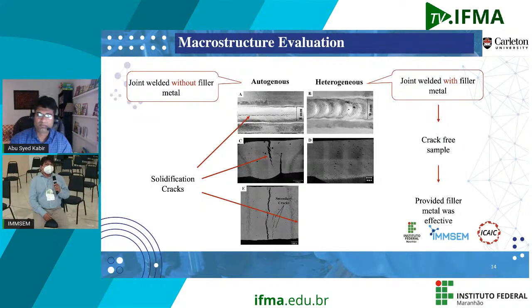So this is the output. We created two different welds. One is autogenous, another one is heterogeneous. Autogenous means we didn't use any filler metal whatsoever. We just joined two 7075 sheets without any filler metals. And in the heterogeneous joint, we welded the sheets with filler metal, and the filler metal was 1.7 weight% titanium carbide nanoparticle infused 7075 filler metal. So we have nanoparticles in the heterogeneous joint, and we don't have any nanoparticles in the autogenous joint.